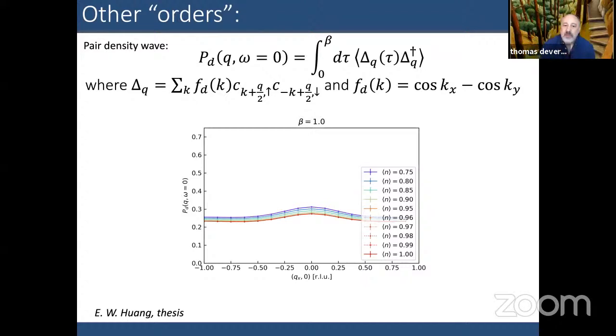So I'll plot the pair field susceptibilities as a function of momentum Q, and I'll show you a little movie, which is just plotting this for different doping and for different temperatures. So here, at large temperatures, beta of one, or the temperature on the order of T, there is a very, very weak peak at around Q equal to zero. I'm just plotting Q along the reciprocal, the bond direction.